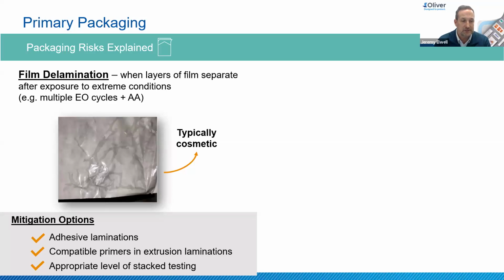So some mitigation options, we talked about these being extrusion laminations, which I'll have a photo of later with a study that we have. A mitigation option is to use an adhesive laminated film, and that's much stronger. It could withstand these extreme environments, but also gas sterilization like chlorine dioxide. And also looking further into extrusion laminations, there are primers that are compatible with extrusion, so you can also consider those for your testing and appropriate levels of stack testing as well. There's a lot of guidance out there. There's a lot of standards we have to follow in the packaging world. Really understanding what testing is necessary and trying to avoid unnecessary stacking of those tests.